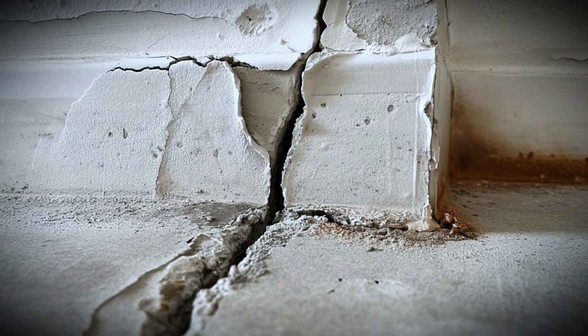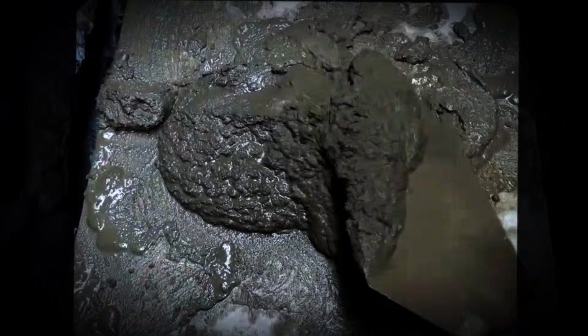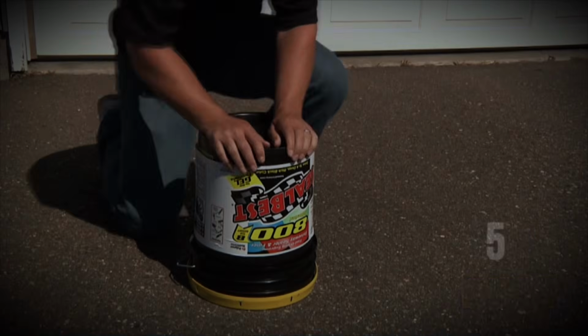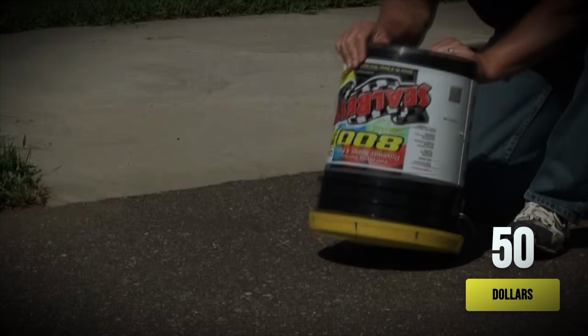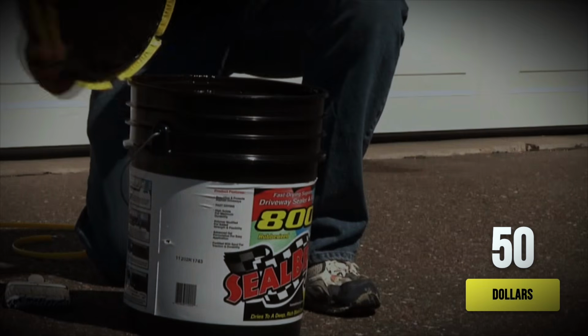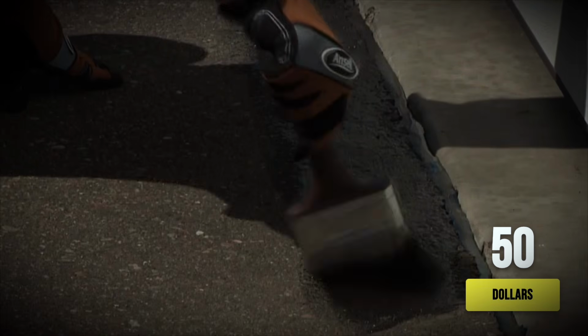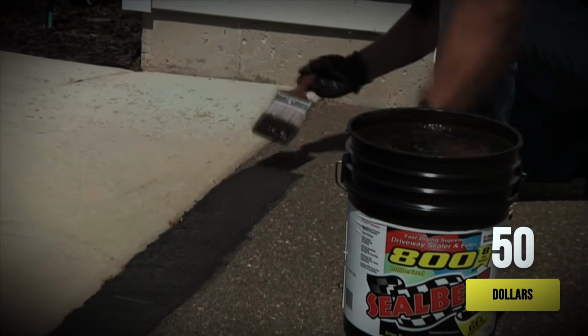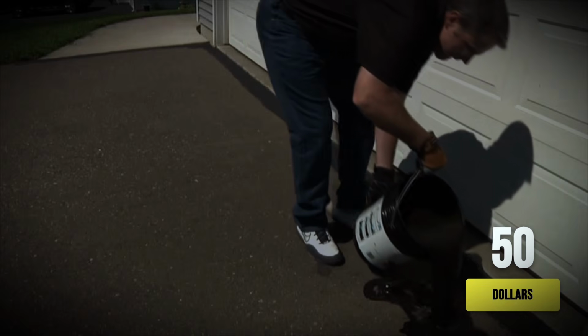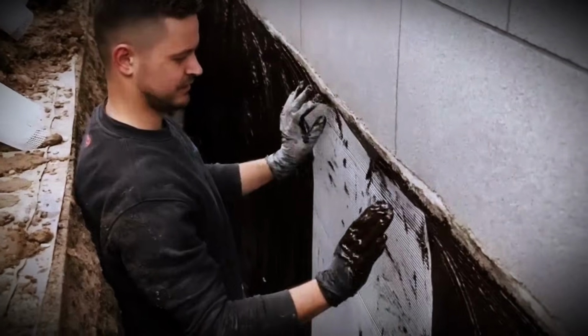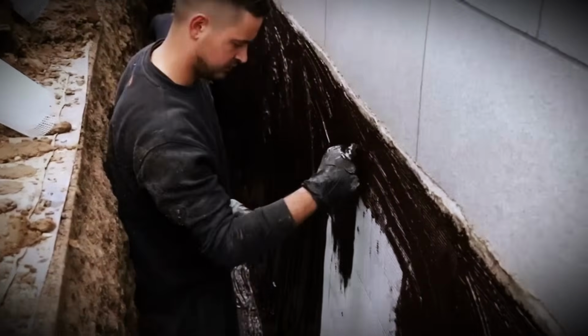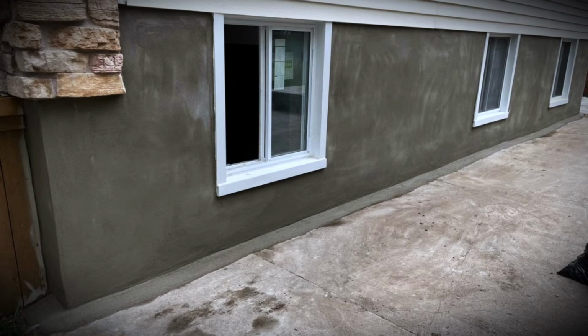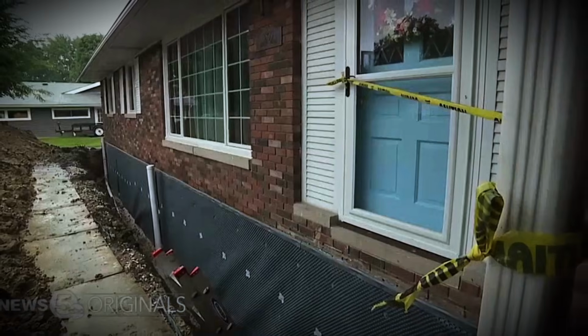And here is what makes this truly frustrating. The original method, the parging and bituminous seal that masons used for decades, would have prevented almost all of these problems for a fraction of the cost. The materials for a modern version of this system, using Portland cement, sand, and a polymer-modified asphalt coating, still cost under $50 for an average residential foundation. The labor takes a day or two, and the result is a positive-side waterproof barrier that will last for the life of the structure. You cannot install it from inside the basement.